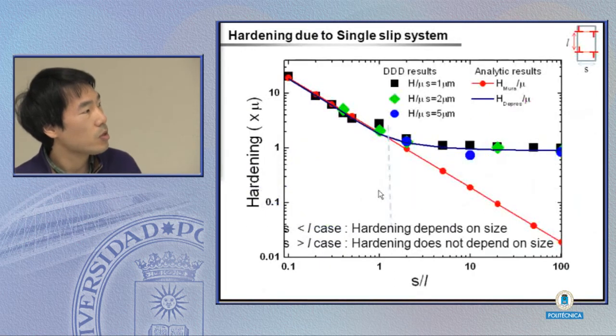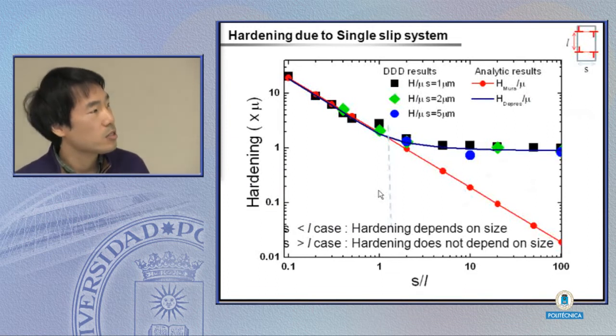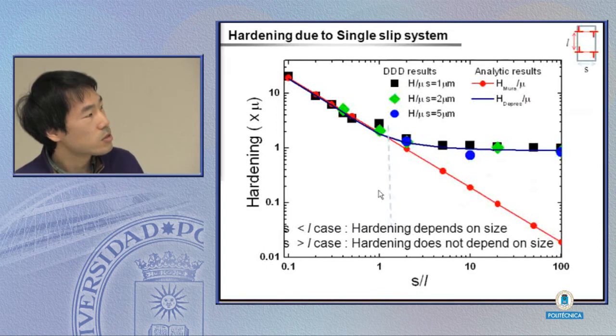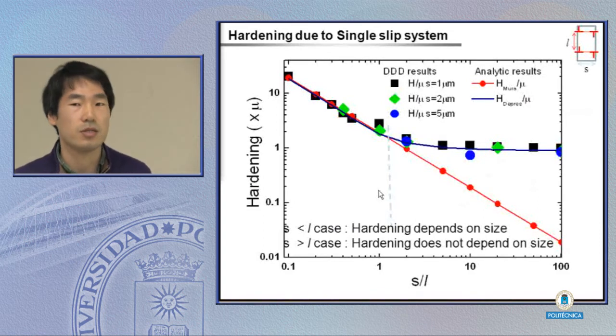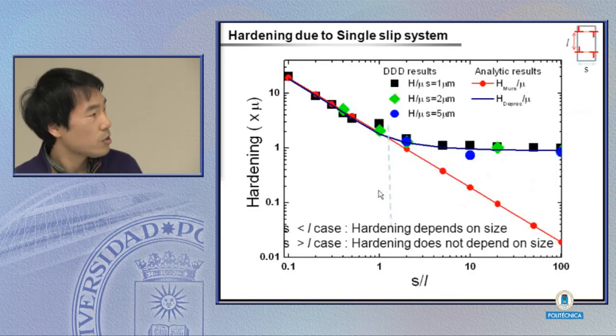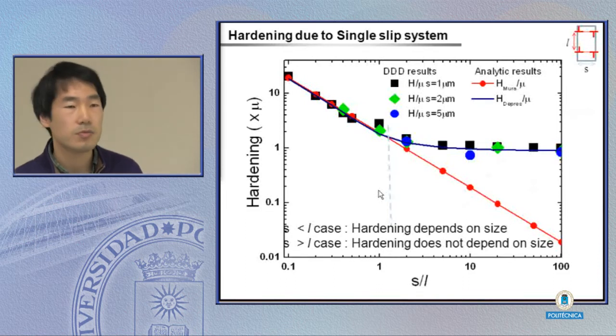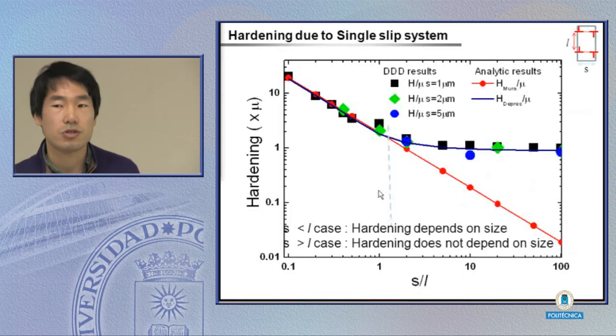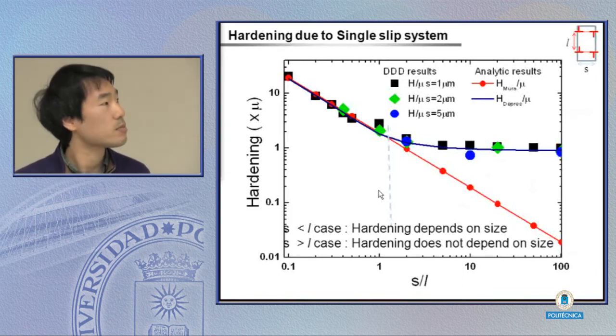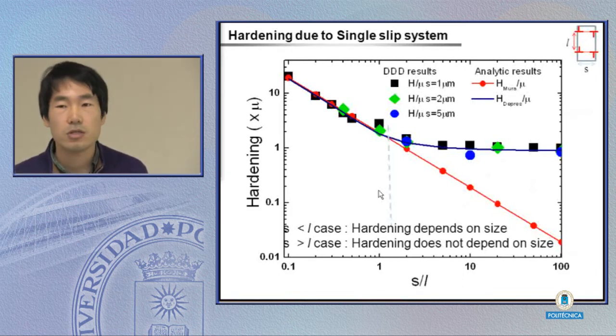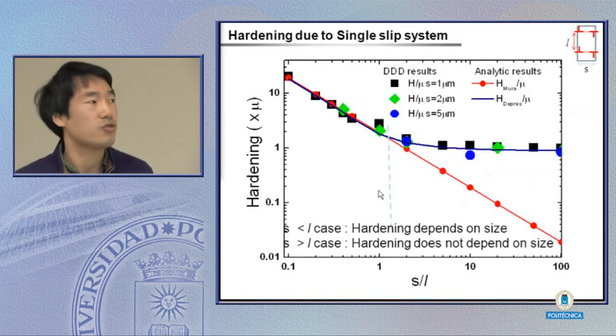The load displacement curve is totally affected by the internal length size. Decreasing the internal length gives more strain with given stress field. So using these two raw data, we can have the work hardening from the slope of the load displacement curve and the GND dispersion from the dislocation structures.